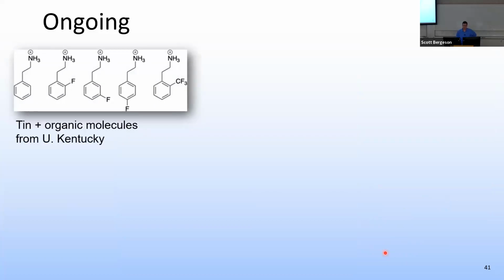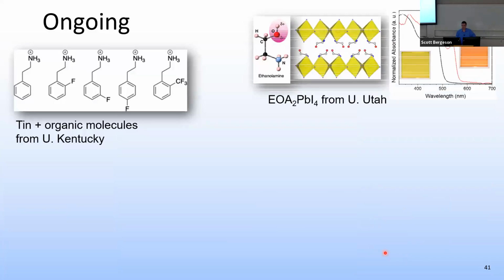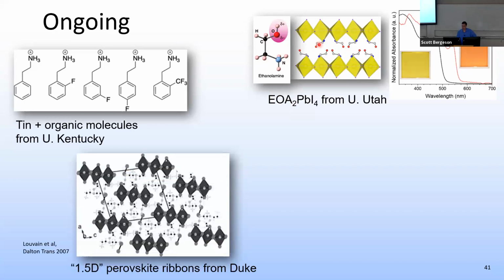We've got partners from the University of Kentucky that are making tin-based perovskites, changing different organic molecules to impact the polarization. We've got University of Utah collaborators that are studying the effects of water on this particular molecule. Water turns out to be a real source of degradation if you want to make these perovskite materials go on the roof of your house. We're not quite there yet.